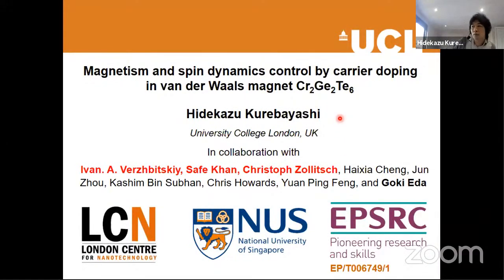Thank you for the opportunity to give our latest results, particularly on this van der Waals system, chromium germanium telluride, where we try to control the magnetism by carrier doping, both in an electrostatic way and also by chemical doping. And if I have time, I'm going to show you the latest results of magnon-photon coupling with a superconductor resonator and also this material, chromium germanium telluride.